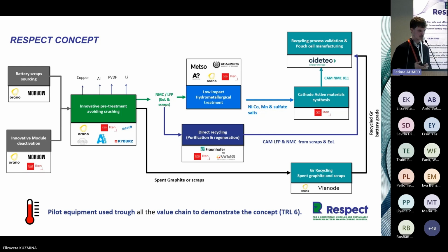So we managed to separate copper, aluminium, binder, lithium, and we have two main output fractions: a fraction containing graphite and a second fraction containing mostly cathode active materials, which can be mostly NMC or LFP depending on the input material. For the graphite, we have one partner, Vianode, located in Norway, who is responsible for the regeneration of this fraction for reuse as new anode materials.